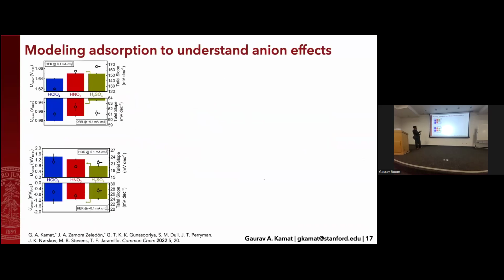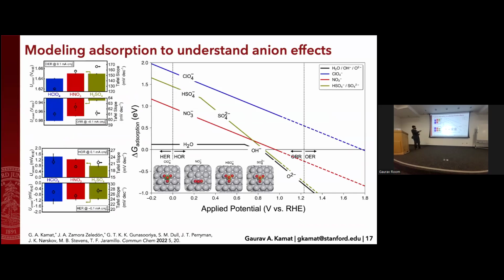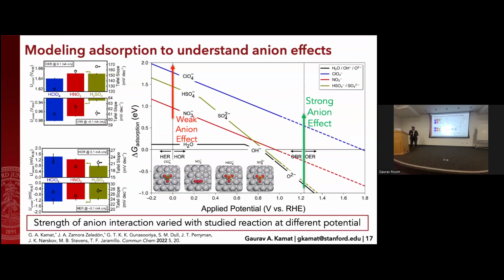So looking at these oxygen-based reactions versus these hydrogen-based reactions, one tool we use to understand why this may be happening is physics-based modeling, specifically with density functional theory. Some collaborators of ours were able to model the delta G of adsorption of these different anions on a platinum surface. What this delta G of adsorption means is as you go lower on this axis, you have a stronger interaction with your surface. As you go higher, you have a weaker interaction with your surface. And one thing you see is right here where the ORR and OER potential range is, you have a strong anion effect because these are interacting a lot more strongly. They're much lower in their delta G adsorption compared to a weak anion effect when you're over here in the HER and HOR range. And so this strength of anion interactions varies at different potentials, and it's an example of competitive adsorption on a platinum electrode that's changing your electrocatalysis in different ways.